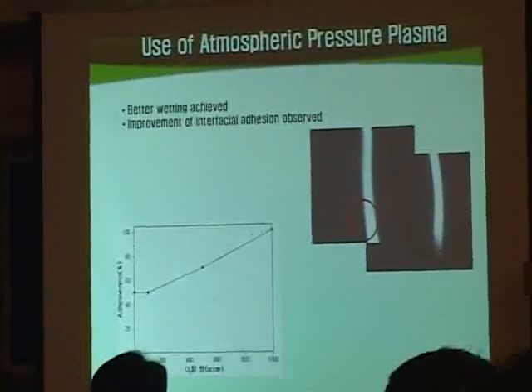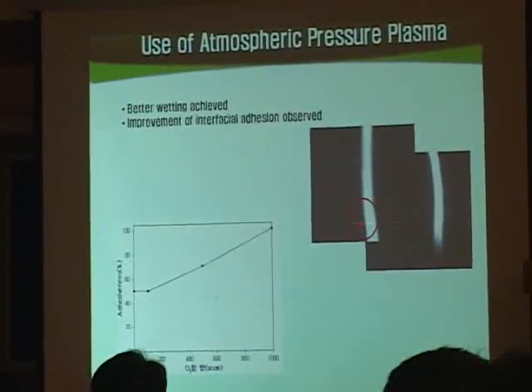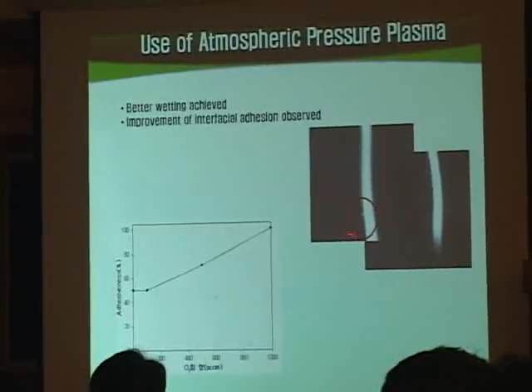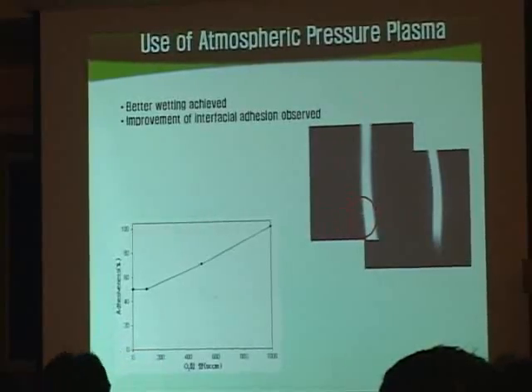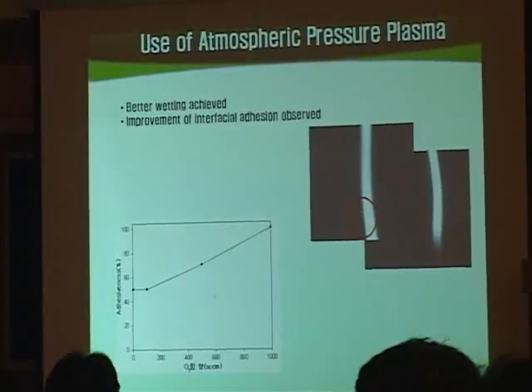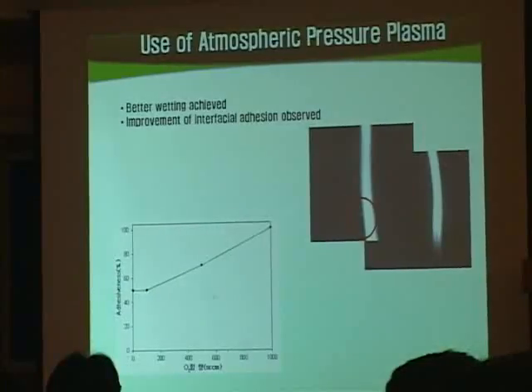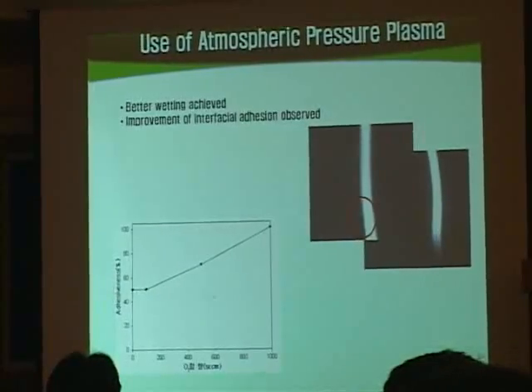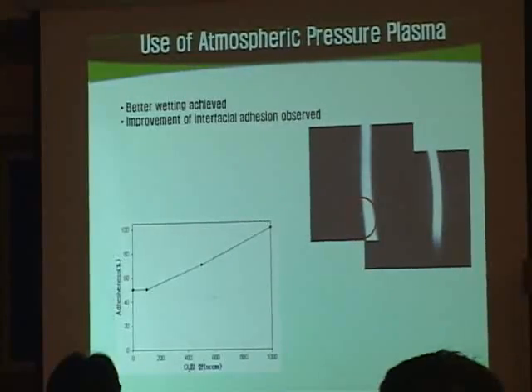And then we achieved a couple of improvements. First of all, wetting. I don't know if you can see here, there are small circles around here. This is a coated surface, and when we coat the organic coat on this substrate, it develops certain pinholes. With atmospheric pressure plasma, we were able to get rid of those pinholes, as well as increase the adhesion property to the complete situation.